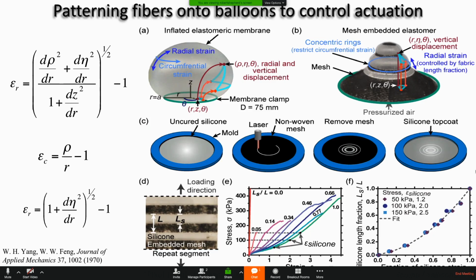What these rings do is when we inflate a balloon, it normally inflates radially and circumferentially. It's very hard to predict a priori what a shape is going to be if you pattern fibers onto it or inextensible material when you're getting inflation in both of these directions. It's not hard to predict when you know you're just going to get radial projections. If you limit the circumferential expansion of these balloons using these inextensible rings, and it's something anybody can do, you can laser cut these rings and then you can just glue them onto rubber sheets. When you inflate them, you just get projections.